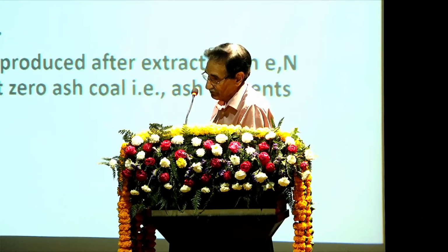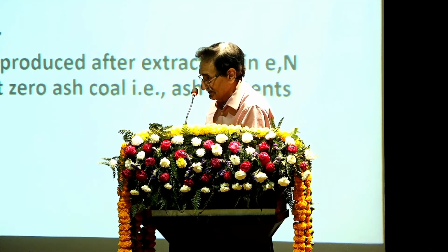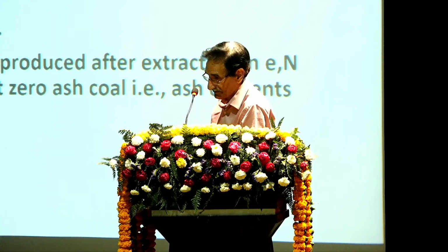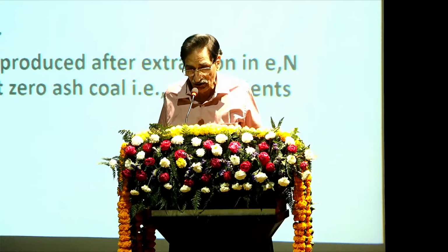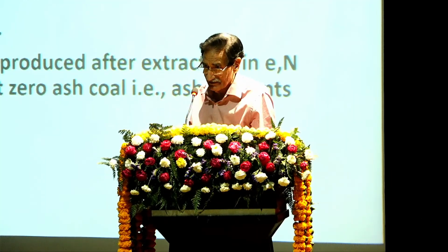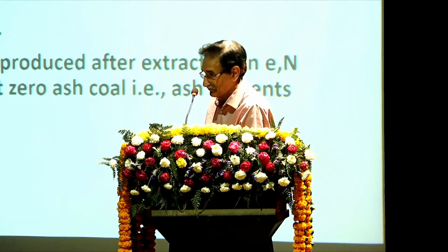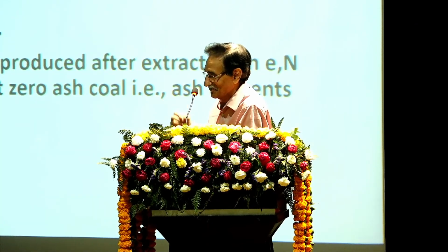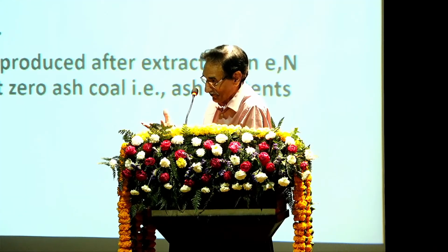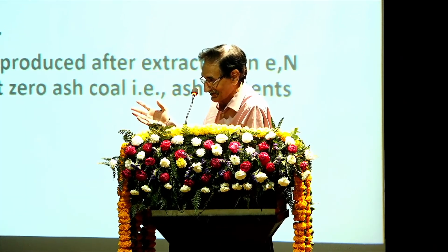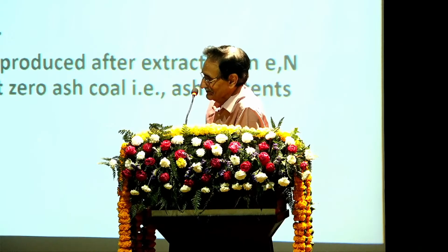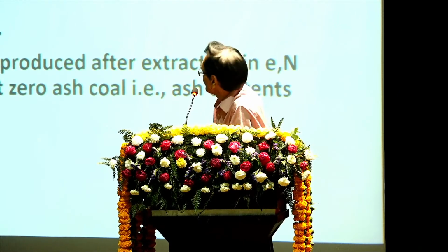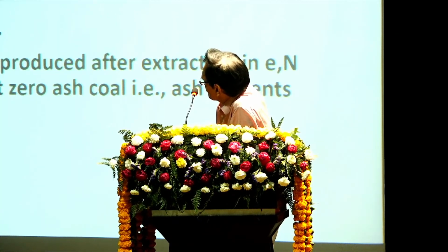We got more than 50% yield of clean coal. We called it super clean coal because it has very little ash. The ash content varied from 0 to 2%. We published that paper, and there was a lot of issue and cry in India. People said that it is something very unusual. How can you have zero ash coal? A lot of discussions went on in CSIR, CIMFR, and DST. They gave us a project. We proved that yes, coal can have zero ash also. In fact, coal had 0 to 2% ash.